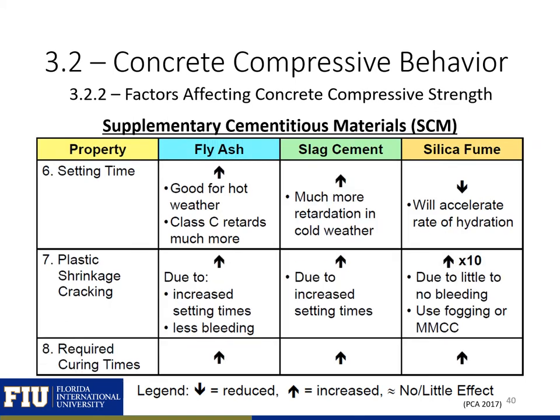Fly ash and slag will both increase the setting time of concrete, while silica fume will slightly accelerate the rate of hydration and the setting time. All three SCMs will increase the plastic shrinkage cracking and increase the required curing times, as water is required for longer periods to fuel pozzolanic and later hydraulic reactions. If you use SCMs, you need to make sure that you cure your concrete properly.